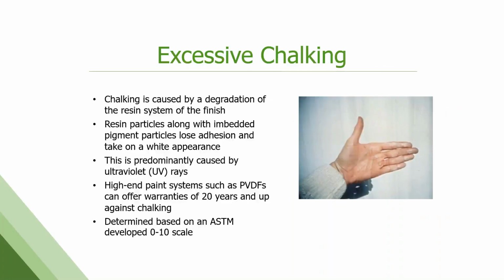So excessive chalking, it's just what it sounds like. It's when a painted surface gets white and chalky and there's this white powder on it that you can usually wipe off with your hand or a rag. What's occurring there is that the resin particle or the polymer backbone is being broken down by UV exposure into little short segments and then can come off the surface, bringing the pigment with it, which is why you get a lightening or a whitening effect.